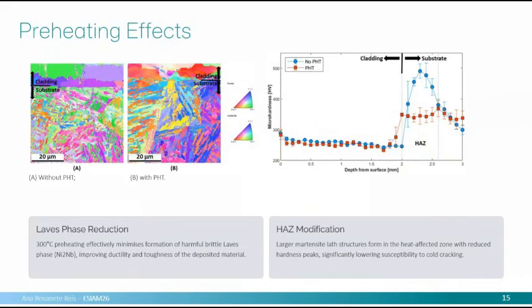And then we went to see results in terms of microstructures and also hardness. What we get is that preheating is very good, because it homogenizes a little bit the interface between the deposition and the base material, so we don't have this proneness to start cracking. But you don't have a very good hardness. We go to 300 HV. So this was good for filling, but not good for the last layers, because you don't have the hardness that we need.